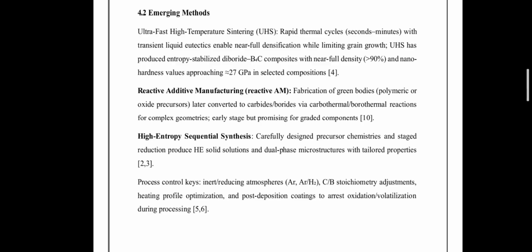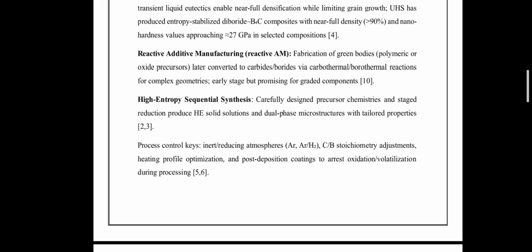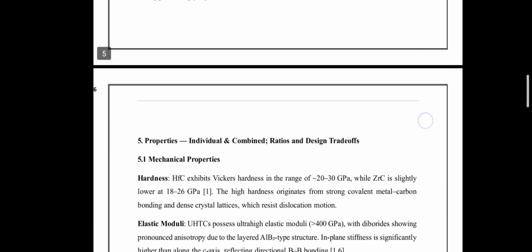The process control considerations that we should keep in mind involve the following. Successful UHT fabrication critically depends upon process control. It includes an inert or mildly reducing atmosphere to suppress oxidation and volatilization, precise carbon and boron stoichiometry to avoid residual oxygen or free carbon, optimized heating profile to balance densification and grain growth, and protective coating or sacrificial layer to limit surface degradation during processing. So these were some fabrication and synthesis routes for the ultra high temperature ceramics.